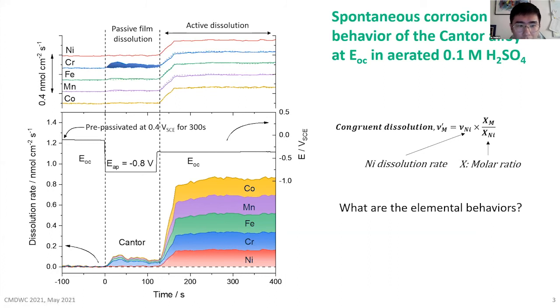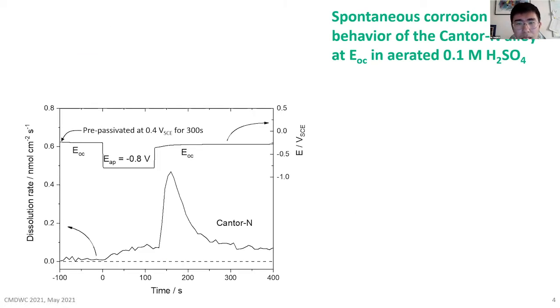And after this step, in the open circuit dissolution, we observed almost congruent dissolution for all the elements. And the same experiment was performed on the Cantor N alloy. So we can see that for this alloy, there is a very different behavior in the third step.